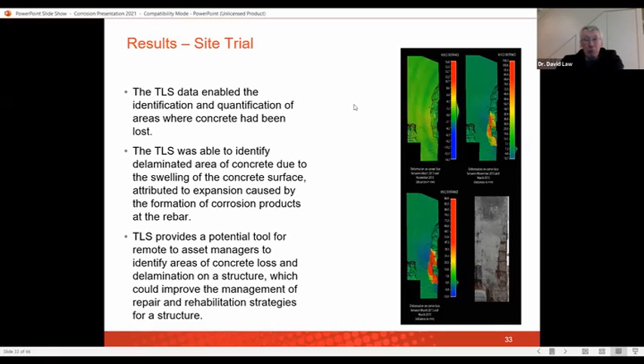This was our wall that we saw over time. And what we saw here, this red zone, is it's actually moving out. So the top one is where we were at the start. And then over time, we saw this red zone. And so this is the end of it. And this is what it looked like. And at the end, a spall fell off. And so what we were seeing is this concrete was debonding and moving towards us over time.